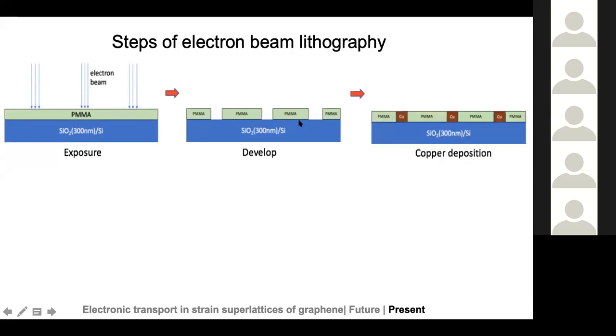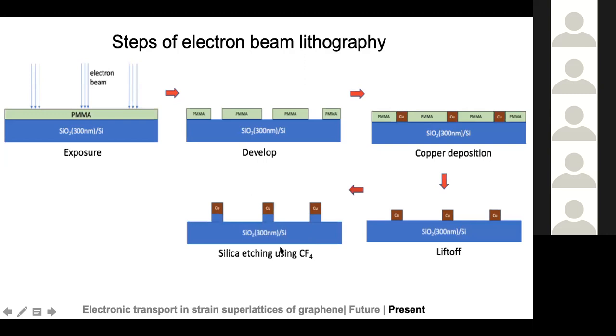The next step, for me, was depositing a metal. I used copper specifically as a mask. What the mask is will be clear to you in just a minute or so. After that, we lift off the rest of the PMMA by using acetone. And so you're left with these copper features on top of your sample. And then we do something called reactive ion etching using carbon tetrafluoride gas, which will react with the particles of silicon dioxide and remove them.